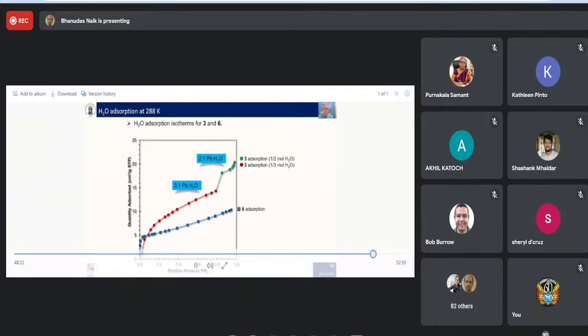Whereas 3 very slowly absorbs here, until you get to the 3:1 ratio. So 3 forms very slowly, goes to 1. And then when you get this ratio here, then it very quickly goes up and down, forming compound 4 at the end. So you basically have a half mole of water forming here, which is about 15, and then the next part here is, I guess, about 12. And here you have about 6 more, which is another third molecule more of water that goes in to form compound 4. So this is very interesting. You can show as well the water absorption of these compounds.